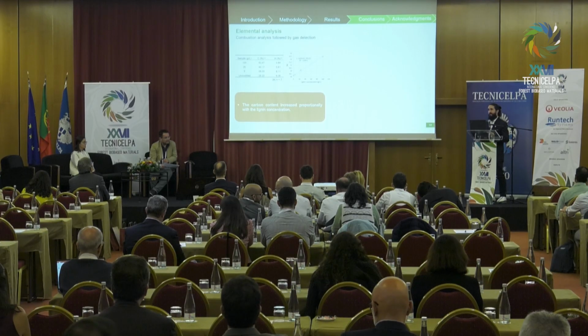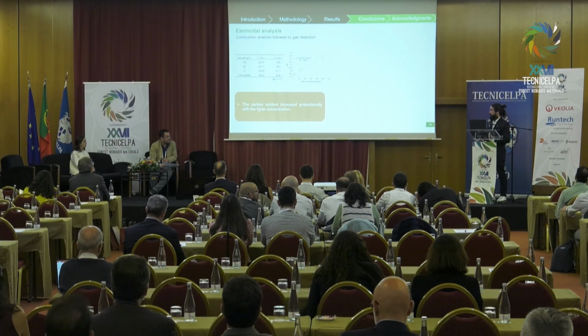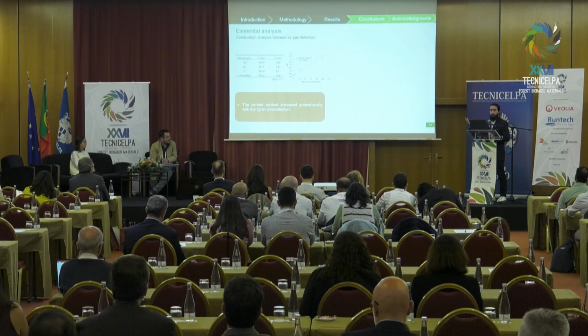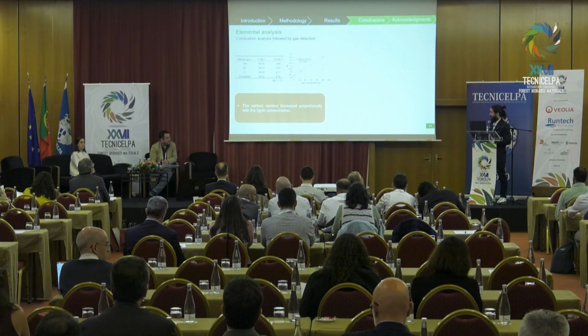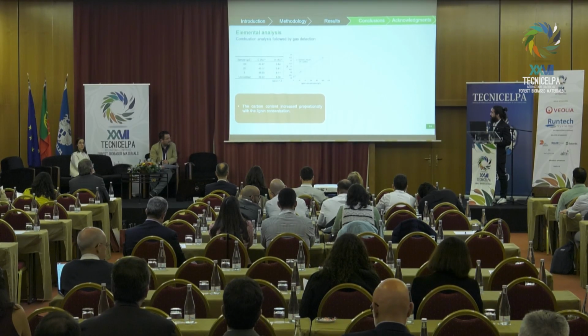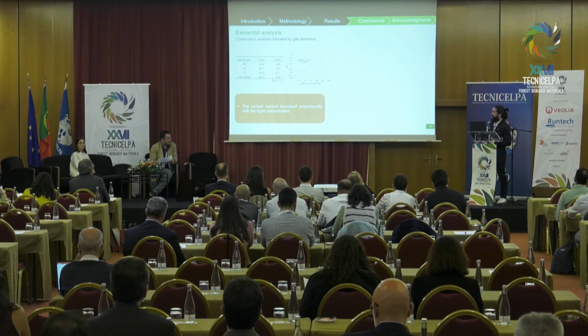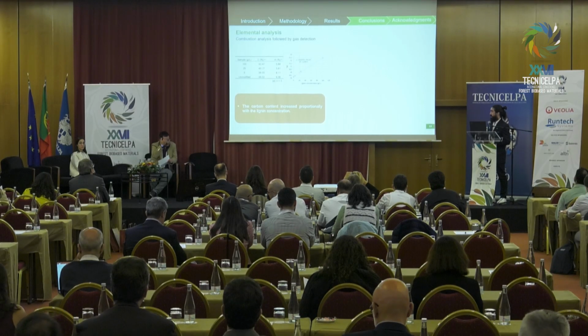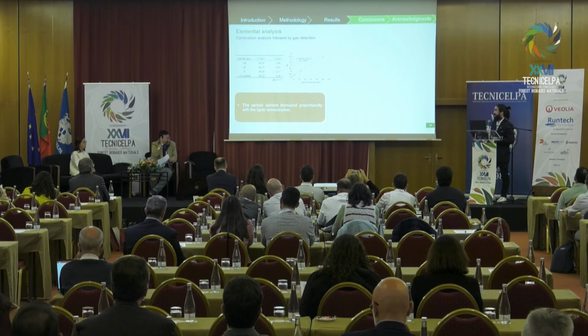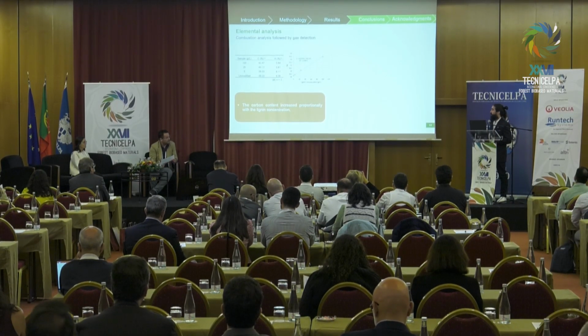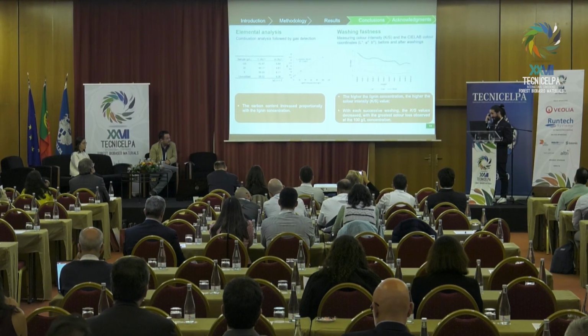Moving on to the elemental analysis, we only present here the carbon and hydrogen results because our lignin and our nonwoven didn't present any nitrogen or sulfur. But as you can see here, as we add more concentration in our solutions, we have almost a perfect linear correlation with percentage of carbon. So it's an indication that we are successfully modifying our nonwovens.